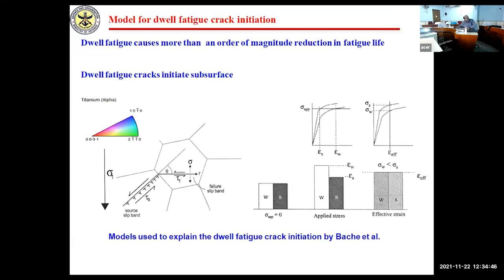I'll show you the exact values. And the other funny thing that happens is this: dwell fatigue cracks initiate subsurface, not on the surface. We have been taught that fatigue cracks initiate on the surface, but dwell fatigue cracks initiate subsurface. Now, how does it happen?